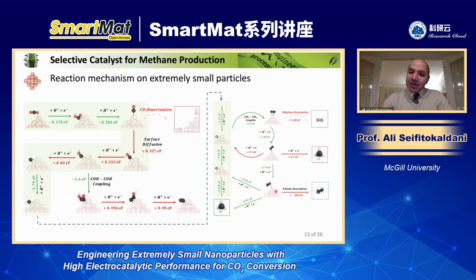And if you increase the temperature further, you can help to observe more ethane. But then what happens, I mean, an even more favorable pathway is once you have the ethane, instead of leaving the surface, it can quickly be converted to methane. So either producing 2 methane, desorbed methane, or 1 methane and then another adsorbed methyl group, which can be further converted into methane through another hydrogenation step. So this observation was telling us now that if we use this extremely small particle, we should expect more methane than ethane.